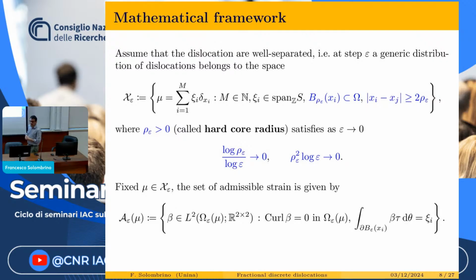furnished with additional conditions. And this is, from a mathematical point of view, one of the technicalities we have to take into account. So this is more for people interested in mathematics. There were some additional conditions that have to be considered, and it would be nice from a variational calculus point of view if one can get rid of them. So forget about the scaling, so you can put some assumptions. The point is that, okay, dislocations can homogenize, so you can have dislocations close to each other. But the condition you have to impose is that they are well separated. So that there is a minimal distance, which you call rho epsilon, this minimal distance is vanishing, so in the limit you can create some diffuse plastic pressure, but it's vanishing at some rate compared to your core radius epsilon.